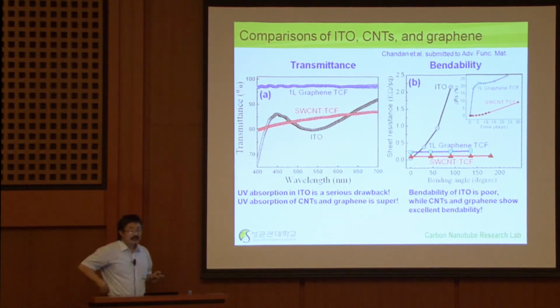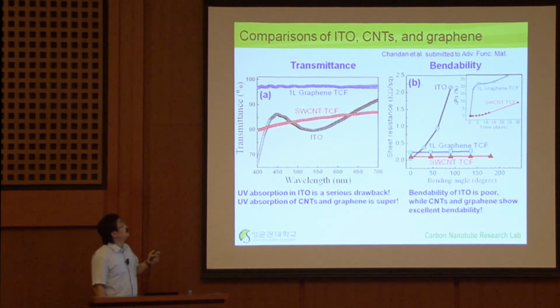So let's talk about this transmittance. If you look at single layer graphene, the transmittance is almost 97%. So each single graphene layer absorbs only 2.5% of light. Whereas carbon nanotubes, the difference is that a single carbon nanotube film has a thick layer, but basically they are quite inert over this wavelength. Whereas ITO has a very strong absorption near the UV region, which is another serious drawback. And then you also have this wavelength dependence in the visible range. So this is a problem.